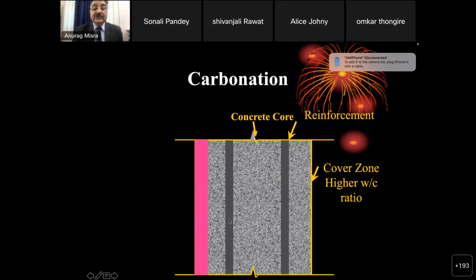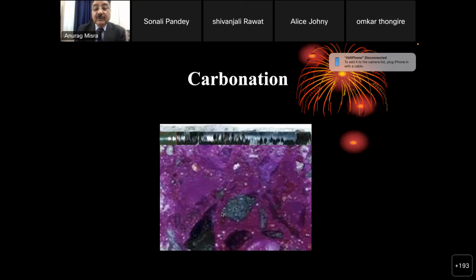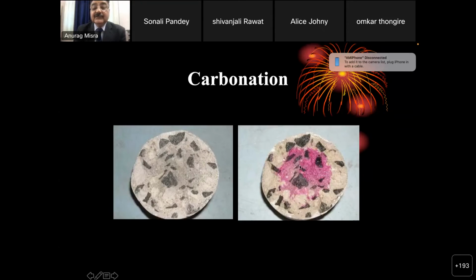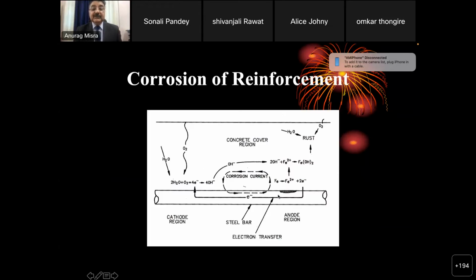As long as it is not reaching the reinforcement, the reinforcement is protected, and as it reaches the reinforcement, the protective passive layer is lost because of the loss of pH, and the corrosion can start. You can see here the phenolphthalein spray test showing that this inner part is not carbonated, whereas the outside is completely carbonated, and the corrosion has started. This is how we do the phenolphthalein test. We took a sample, and if you spray phenolphthalein, you are able to gauge how much carbonation of concrete has happened.